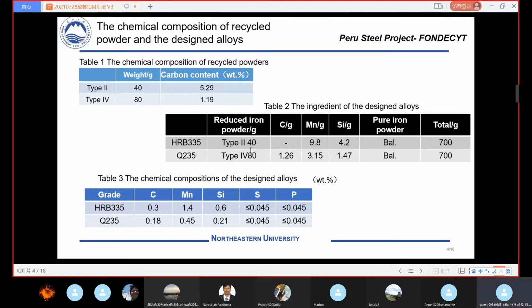Using the recycled type 2 and type 4 powders, we designed two traditional alloys, HRB 335 and Q235. Table 2 is the ingredient of the designed alloys. We use part of the powder as reduced iron powder. Here Type II, 40 gram, to prepare the HRB 335, and Type IV, 80 gram, to prepare the Q235. Because we need to design the alloys, we need to add extra elements. The weight is shown here.